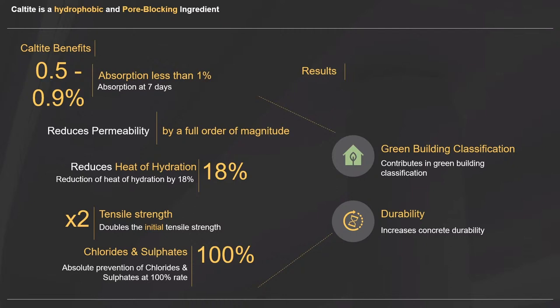It depends on other factors, the cement content and the strength of the mix, but that's the general order of absorption that you will get. Permeability, which I said earlier, is actually a measure of the movement of water through a fully saturated concrete, so you very seldom actually look at permeability in its true sense. But it's usually expressed as a permeability coefficient, and the inclusion of an HPI will improve that by a full